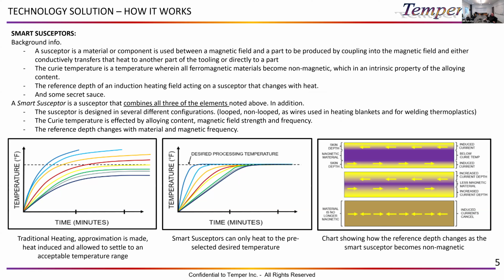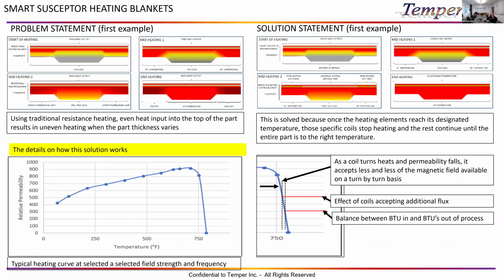So as you can see here, in the lower left-hand corner, this is a traditional resistive heating methodology, where a thin section of the tool heats up very quickly, and the thick area where there's a big heat sink heats up slowly. With the smart susceptor process, it just goes up and it flatlines, right? And so the chemical composition of the material is probably the most important. Then you have the reference depth of the induction heating, the frequency of the field, and the thickness of the material, which are all elements that make a smart susceptor. So you say, well, why is this important?